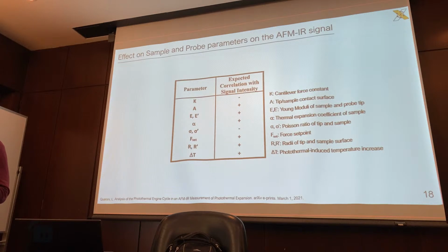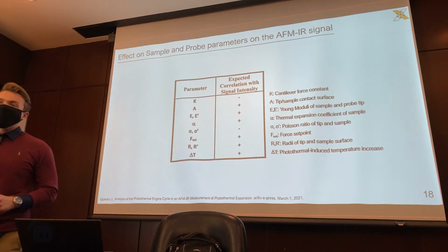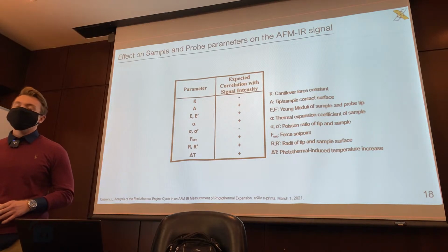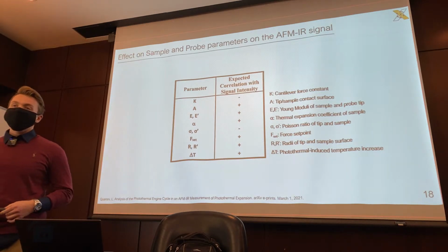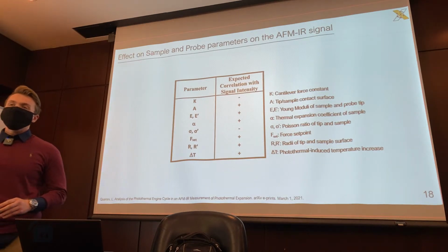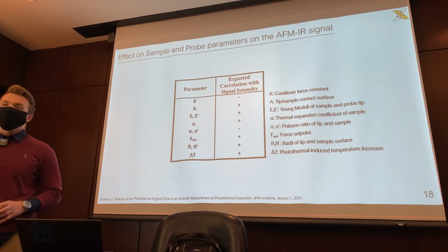Yeah, I was just thinking back to the dip, right? You have the cantilever up above the sample, and you have that decay in temperature, so you have a rapid decay in thermal expansion. And there's that lag time. With a stiffer cantilever, that lag time is going to be less, so you see that decay.